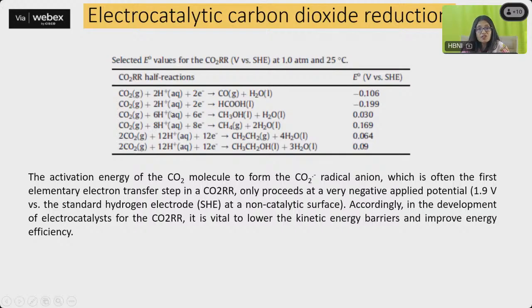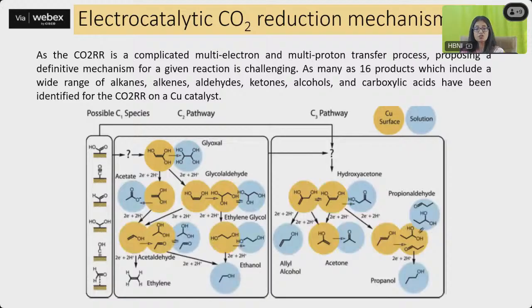But the biggest problem is the activation energy of the carbon dioxide molecule to form this radical anion, CO2 dot minus. This radical anion forming is the biggest problem because it has a very high activation energy, and this is often the first elementary electron transfer step in a carbon dioxide reduction process. The CO2RR is the carbon dioxide reduction reaction, and this proceeds at a very negative applied potential at a non-catalytic surface. So if you have to develop an electrocatalyst for this carbon dioxide reduction reaction, it is vital to lower the kinetic energy barrier and improve the energy efficiency of this process.